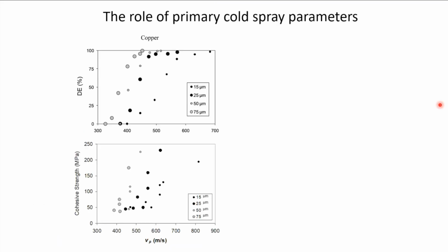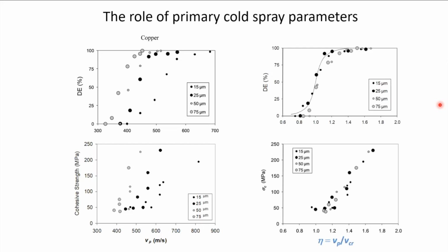So we thought about looking at this from a bit more physical point of view. We plotted deposition efficiency, which is how much you get deposited out of how much particle, versus various parameters, including the particle size and the particle velocity. So you have a multi-dimensional space, and then you end up with a lot of scattered data points on any diagram that you look at. However, if you simply divide the particle velocity by the critical velocity, you end up with a dimensionless parameter we call eta. And you realize that most of these scattered data points collapse onto one line or one curve.